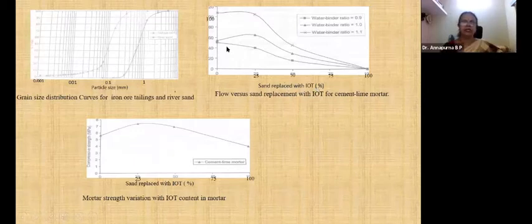Here this is sand replaced with IOT. This is the flow percent. The water binder ratio is 0.9 and 1.1. When the water binder ratio is 0.9, the flow percentage is less for different replacement levels, and as the water binder ratio increases, the flow percentage also increases. This is a graph for compressive strength, for 0, 25, 50, 75, and 100% replacement of the IOT. It is seen that 25% replacement of IOT shows the maximum increase, but up to 50% there is no decrease in the strength.